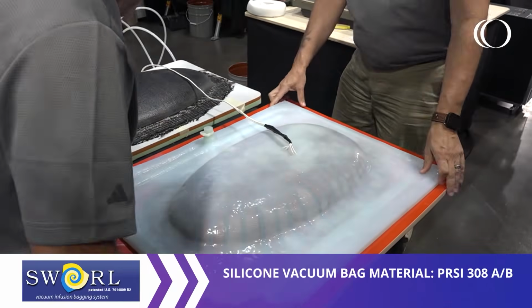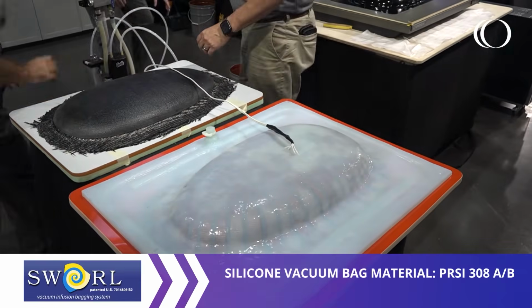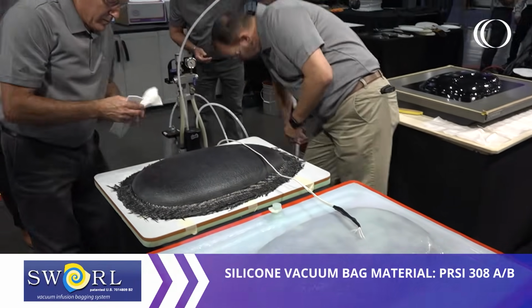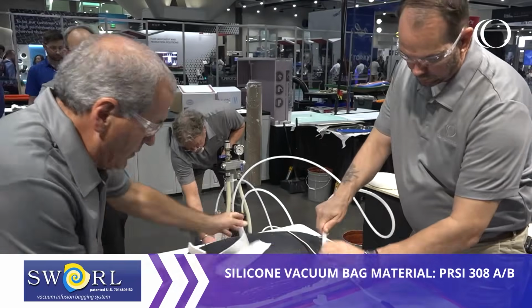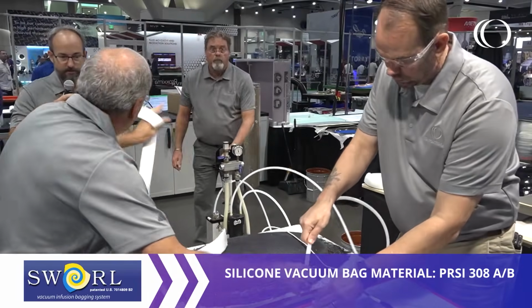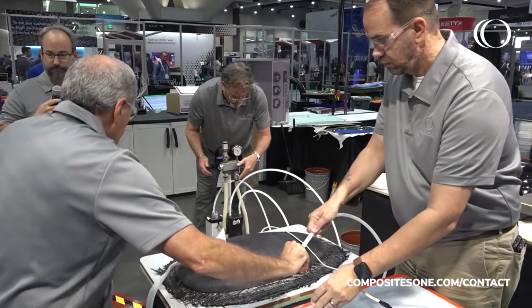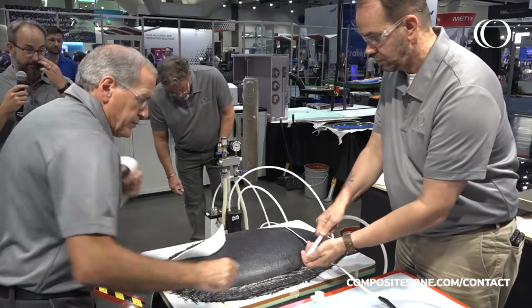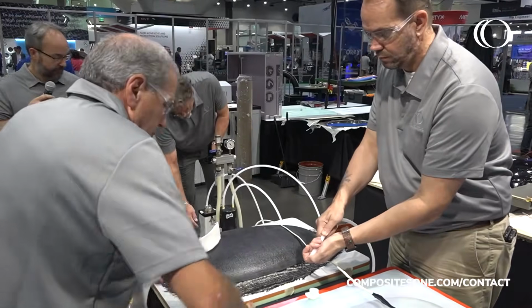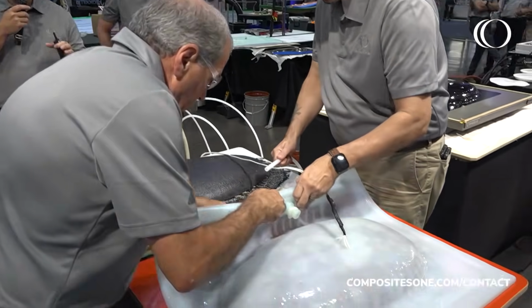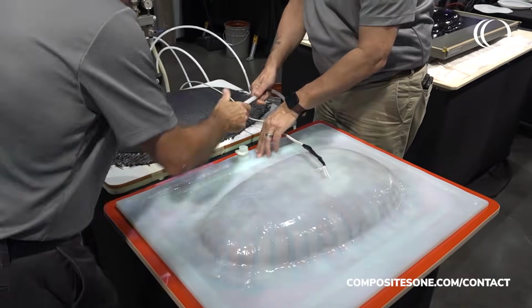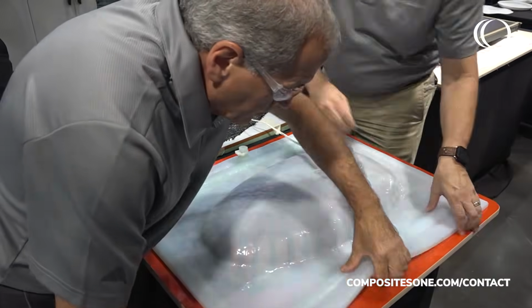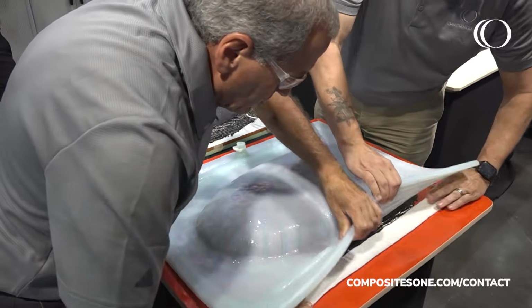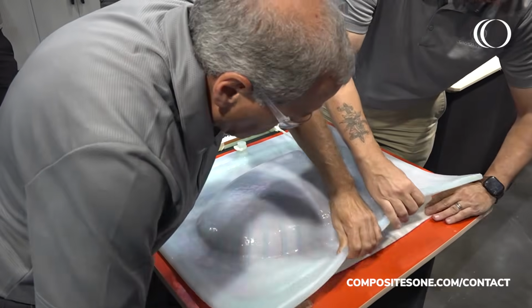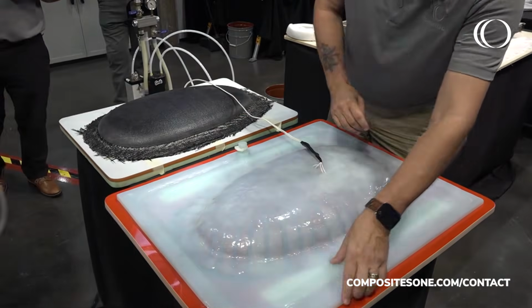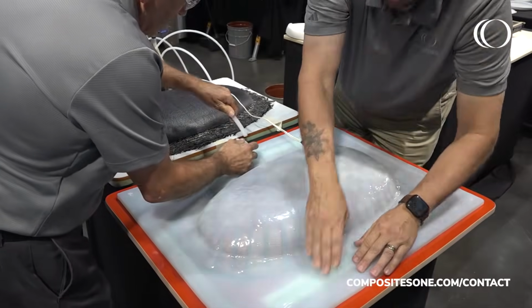So the binder is heat activated. So what we're using today is a silicone vacuum bag with an integrated resistive heater. And so that'll heat our preform to the activation temperature, which is about 200 degrees. And then that will set the binder, and then the preform will maintain its shape. So we can lay up several heavy plies on complex geometry and create a preform. And these preforms are good for many different processes, including vacuum infusion, VARTM, high pressure RTM, and others.